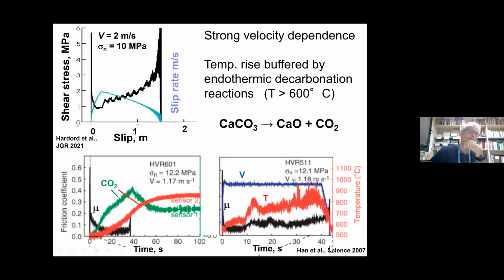Han did this relevant paper in Science, shearing the same marbles many years ago, and he was also measuring the CO2 emission. This is something we did to show that you have this kind of reaction going on. He was measuring the temperature. Now we have better data for all these things. But the point is that we have chemical reactions. Breakdown of calcite to produce lime and CO2. This happens at more than 600 Celsius. And then if you shear more, at some point you will melt the lime.